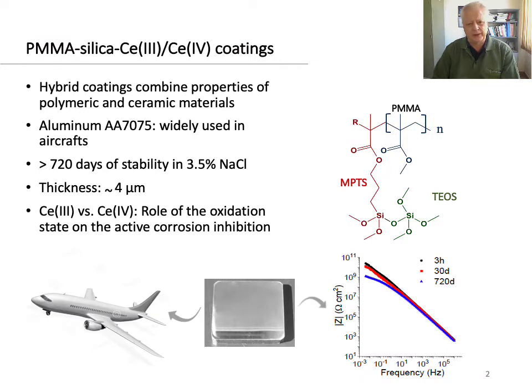Now, the organic and inorganic hybrid coatings combine properties of the polymeric phase, such as processability, transparency, and hydrophobicity, with a high mechanical, thermal, and chemical stability of ceramic materials, such as silica, which also provide excellent adhesion to metallic substrates. This is possible by adding a certain amount of a coupling molecule that links covalently both phases. In this way, contracting the structure, creating a dense network, and providing covalent bonding to the metallic substrate.